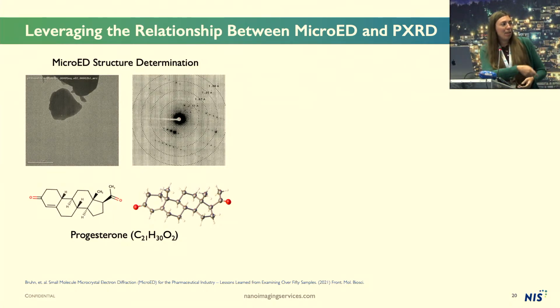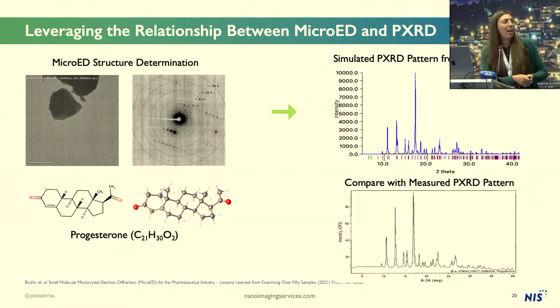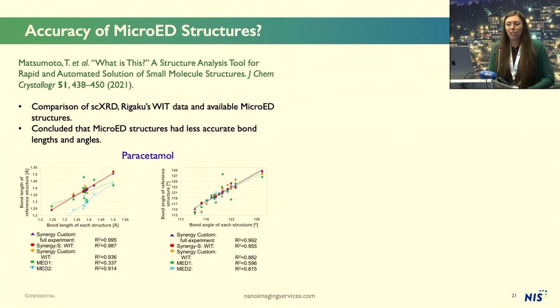So you can take a microED structure, this is progesterone, a structure that we solved, and you can take these coordinates and plug it into Mercury and generate a predicted powder diffraction pattern. Which is great, but it's even better when you combine it with a measured powder diffraction pattern and compare these two spectra and understand the relationship between the structure you solved and your bulk material. Do they line up? Is there another phase in there? That sort of stuff.